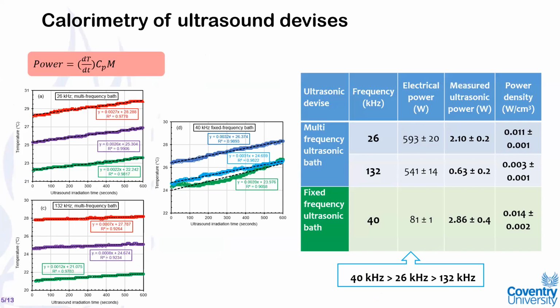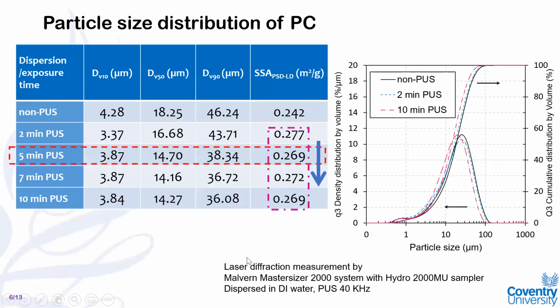The first important step was knowing how much real energy would be dissipated into the system by the ultrasound systems used in this research. As you can see here, the 40 kilohertz small fixed frequency bath used for particle size distribution showed the higher power density of sonication energy, followed by 26 kilohertz and 132 kilohertz applied by the multi-frequency ultrasonic bath. These two frequencies were only applied to cement paste and mortars, and the 40 kilohertz was used only for the particle size distribution study.